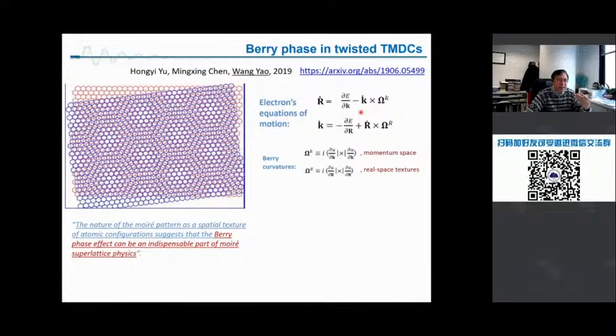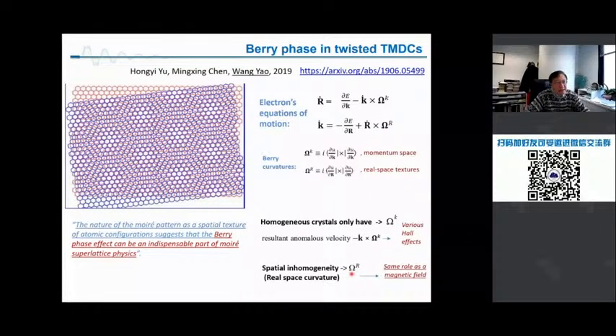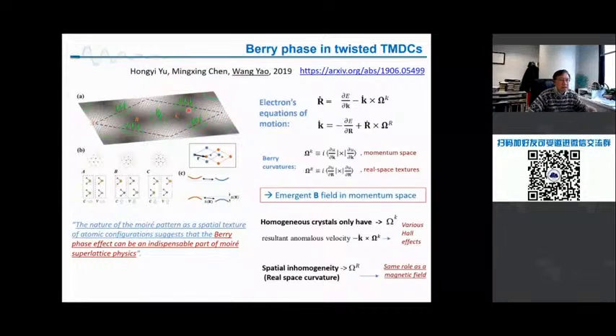In momentum space, you see this kind of terms. In real space, for discrete materials, you see similar terms. For homogeneous materials, you have inversion symmetry breaking. You see this Berry curvature term, and that causes, let's say, the valley Hall effect and so on. And with spatial inhomogeneity, in this kind of Moiré patterns, that causes additional terms. Now, this term is similar to the Berry curvature, and that behaves like a magnetic field. So this is the plot of the pseudo-magnetic field in this kind of materials.